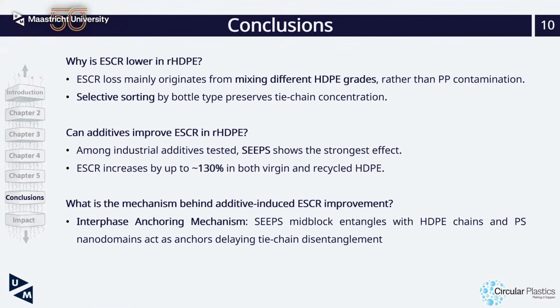In summary, we started with 3 main questions and end with 3 main conclusions. First, loss of ESCR in recycled HDPE mainly originates from mixing different HDPE grades rather than from simply PP contamination. This means that sorting based on bottle type could preserve the tie chain concentration and improve ESCR in the recyclates.